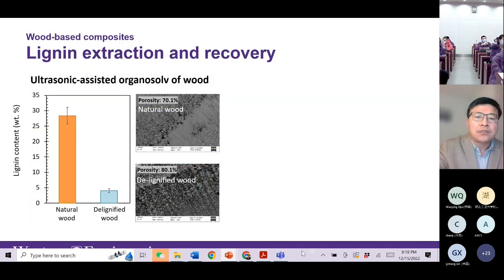And this slide shows the morphologies. Natural wood has 70% porosity, and after removing lignin, we improve the porosity to 80%. The lignin content is reduced from about 30% to about 5%. So we significantly remove the lignin using the ultrasonic-assisted organosolv method, using an organic solvent to extract the lignin.